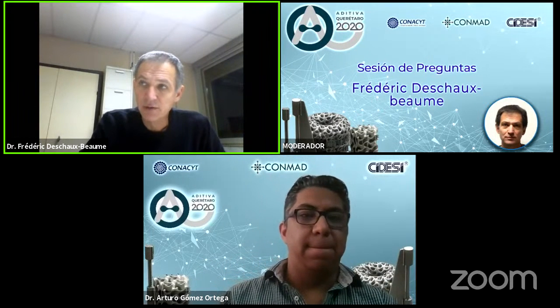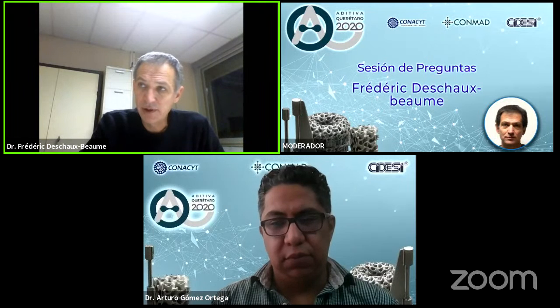For the aluminum, we have no problem, because thanks to the arc process, the oxide layer that forms on the surface is eliminated thanks to the electrical arc. So there is no problem with aluminum alloys concerning the oxidation. With titanium, it's a real problem.